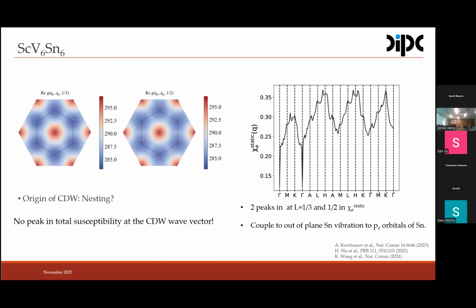Still, if we have electron-phonon interaction, we do not only need a momentum dependence of the electron-phonon interaction, but we also need electrons to interact with phonons, right? So if we look at the electronic susceptibility, we actually do not find any maximum, any peak at the propagation vector of the charge order, not even in the real or imaginary part of the electronic susceptibility, which is somewhat weird. But if we orbitally resolve the electronic susceptibility, and plot the real part which comes from the p_z orbitals of tin, we can see how the electronic susceptibility peaks at the H point of the Brillouin zone. So essentially what we are dealing with here is a momentum dependent electron-phonon interaction, where the out-of-plane vibration of the trigonal tin couples to the p_z orbitals of tin.